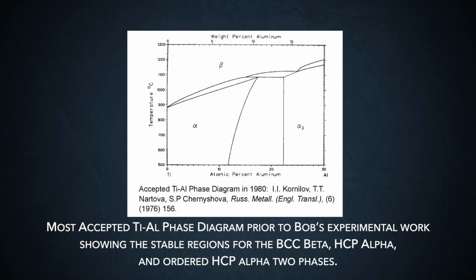body-centered cubic structure. At low temperatures, it was also well known that at small aluminum contents, again, a nice solid solution of aluminum and titanium, but now in a hexagonal close-packed structure. This was called the alpha phase. That body-centered cubic phase at high temperature is called the beta phase.